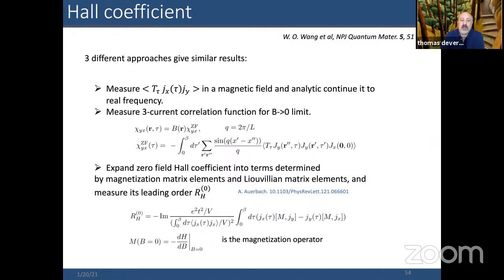And so let me close with the Hall coefficient to show you that it is difficult to calculate, although it's easy to measure. There are three different approaches that one can take in calculating the Hall coefficient. One is just to put in a magnetic field and run your quantum Monte Carlo with the magnetic field. There's nothing wrong with doing that. You're allowed to do it in the algorithm. Your code just becomes complex, but it's straightforward to do. That's valid for any magnetic field.